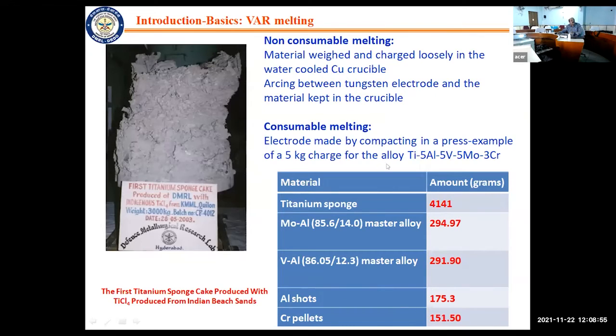And here I'm just showing you how the charge calculation is done. Suppose I want to melt titanium, aluminum 5, vanadium 5, moly 5, chromium 3. These are all weight percentages. This is a 5553 alloy. So you take titanium sponge. Suppose you want to make a 5 kg electrode. You have this much of titanium sponge and this much. Now you have to add moly and you have to add vanadium. Now the moly and vanadium both have higher melting points and higher density as compared to titanium.